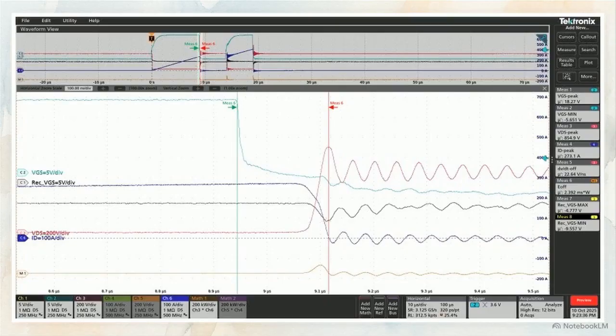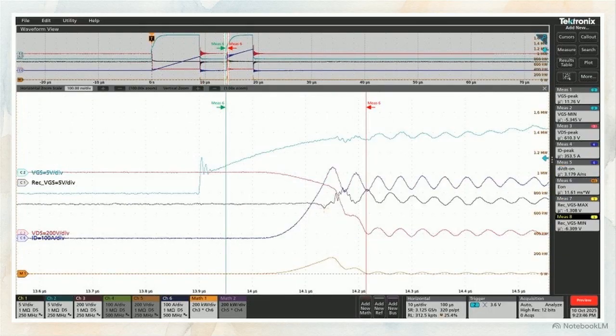This chart displays the turn-off transient at 270 amps. Notice the exact intersection of the falling drain current in blue and rising drain source voltage in orange. With voltage slopes exceeding 20 kilovolts per microsecond, the calculated E-off energy is extremely low, measuring just 2.4 millijoules. This next chart shows the corresponding turn-on transient at the 270 amp load. The timing markers isolate the current rise time, revealing an incredibly steep slope yielding an E-on of just 11.61 millijoules. Even scaled to 540 amps, total switching losses remain tightly controlled.